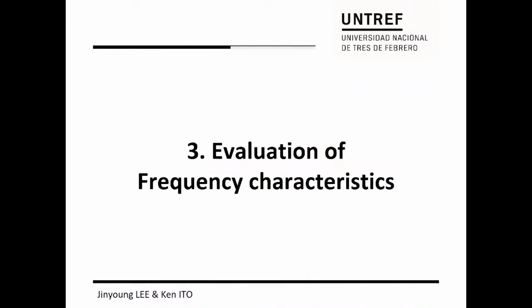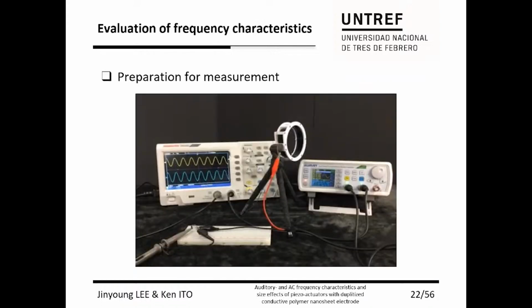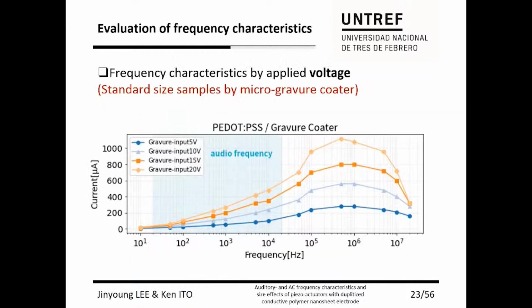Next, we evaluate the AC characteristic of those actuators. We apply the sinusoidal voltage signal to the piezo ribbon actuator and measure the current response. First, we measure the frequency response of a standard sample made by micro gravure coater with various voltage amplitude. The following are the results of 5, 10, 15, and 20 volts input from the bottom.